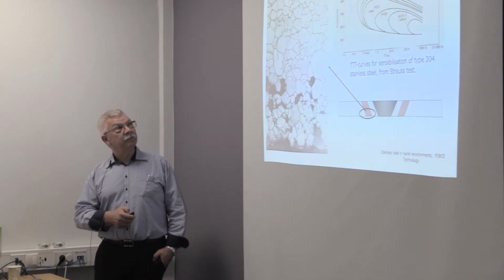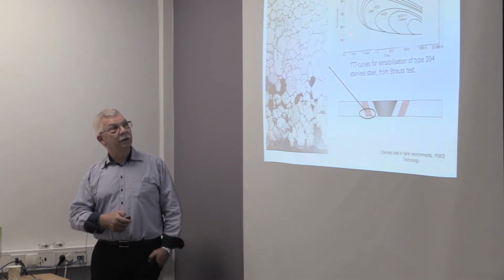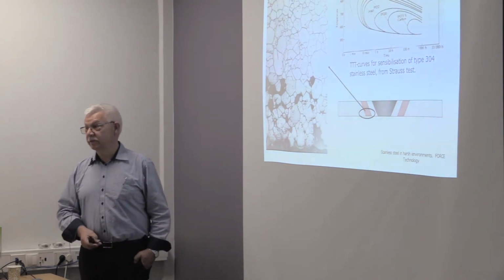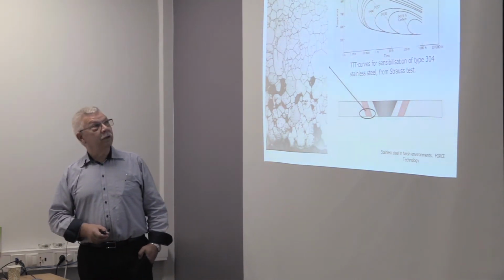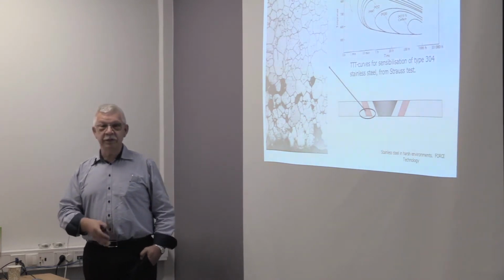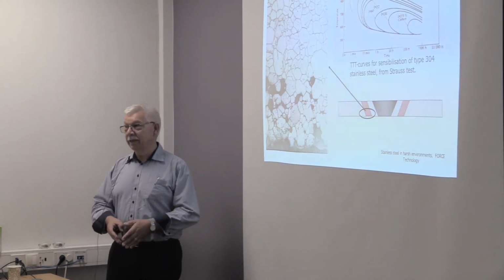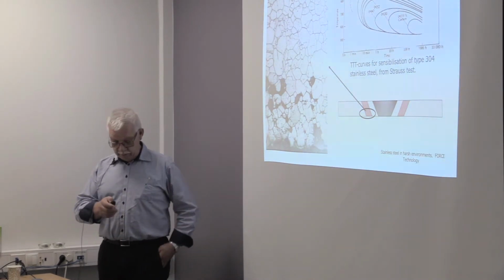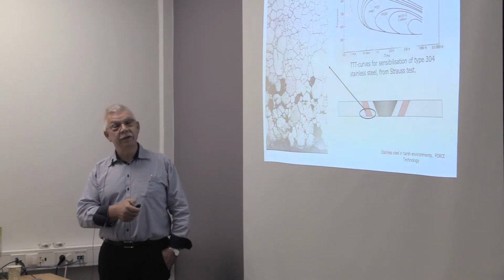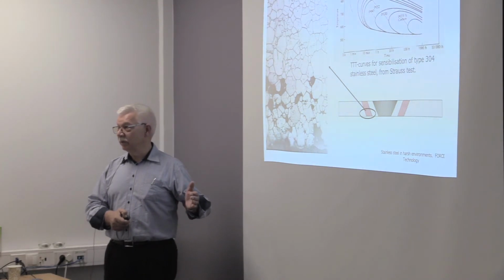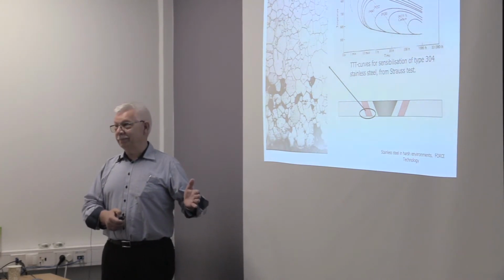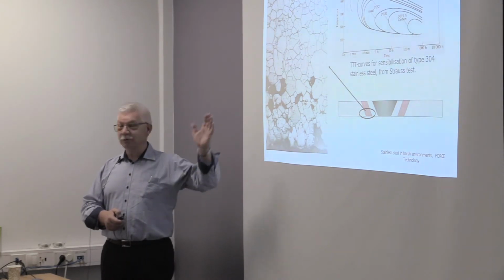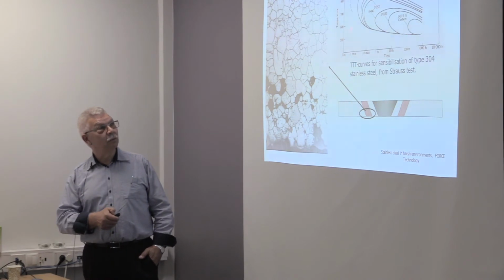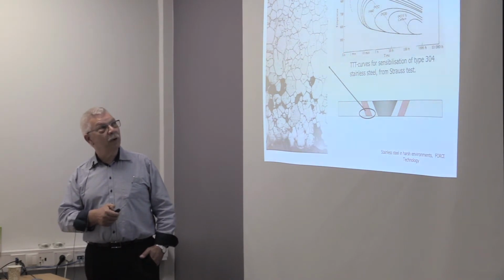And what we can see here is that if we have 0.08 in carbon, then approximately half a minute at 800 degrees C would make the material fail this test. And unfortunately, that's the limit. If you order 304 stainless steel without the L on, then you can have 0.08 in carbon. That's the limit for that designation. Usually you will get better, but in fact you haven't ordered it, so you could also get something that poor. And it's very problematic to weld without being in this field for more than half a minute.